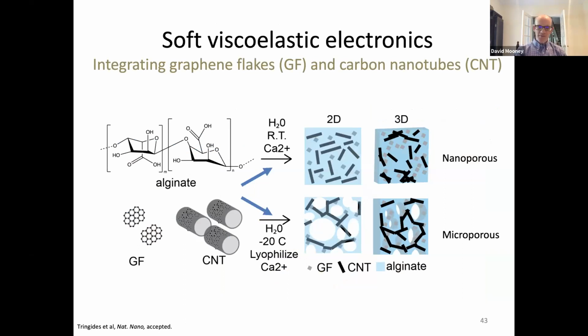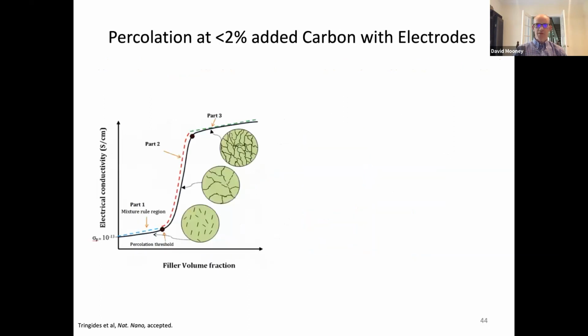Now, in terms of the electronics, the approach we're taking is again to use a hydrogel based on alginate, but we're combining it with carbon nanomaterials, both graphene and carbon nanotubes. And we incorporate these into the material. The premise is if we can get percolation of the particles throughout the network, we have a path for conductivity. The way we're pursuing this is instead of creating a typical nanoporous hydrogel, we purposely make the material microporous through a cryogelation process, so that creates significant pores within the material, concentrates the carbon material in the walls, and enhances our ability to induce percolation at a low solids content of the carbon material.